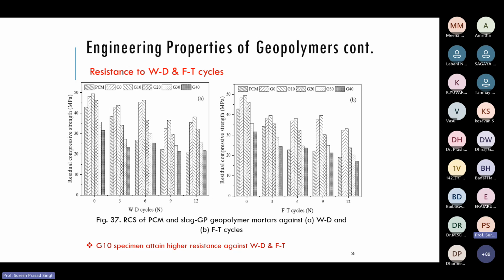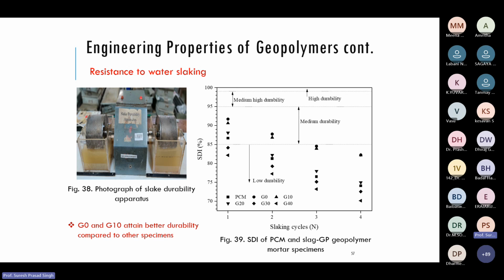The geopolymer mortars are strong, good durable material compared to cement, against high temperature exposure, wetting, drying, freezing, thawing cycles, with less mass loss, as well as very good retention of strength. This is the conventional soundness durability test, what you do for the aggregates and all these things. Similar results are also there. G10 contributes better durability compared to the other geopolymer concrete or the geopolymer mortar. We have not shown the concrete here. Geopolymer mortar is much more resistant to all the weathering actions we have studied compared to the conventional cement and all these things.